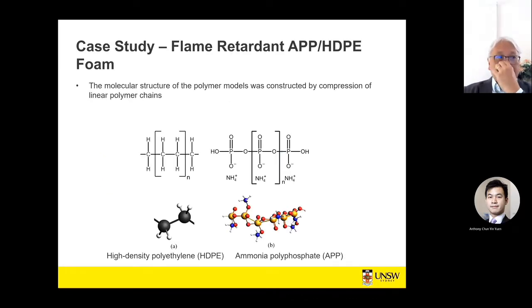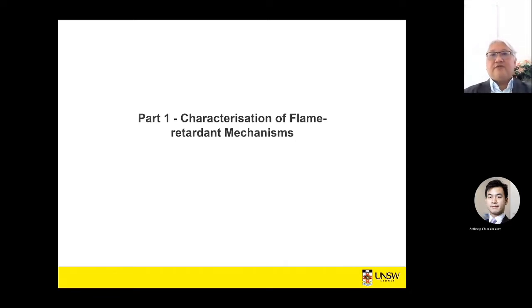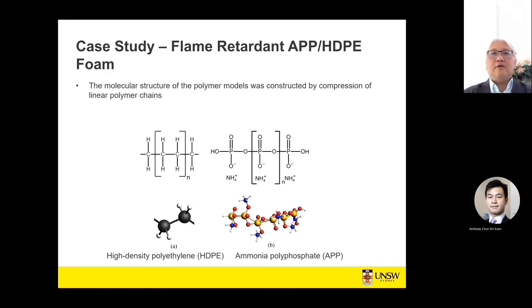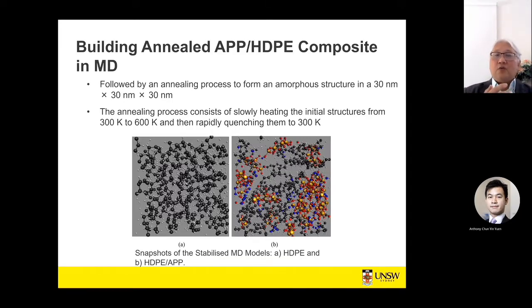Another thing that I'd like to present here is the characterization of flame retardant mechanism. What we have done here is use molecular dynamics to look at the introduction of APP. As all of you know, APP, ammonium polyphosphate, is heavily used in a lot of flame retardants nowadays. It's one of the widely used flame retardants. So what we wanted to do is develop polymer composites containing APP. Again, we followed the annealing process, and the result is that we combine it with HDPE, and the APP is filled within the polymer matrix